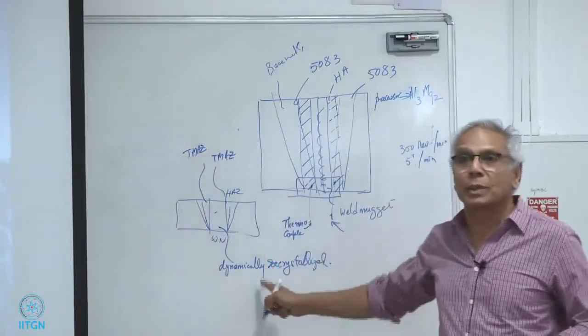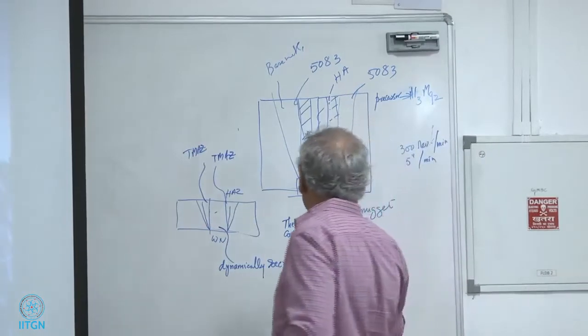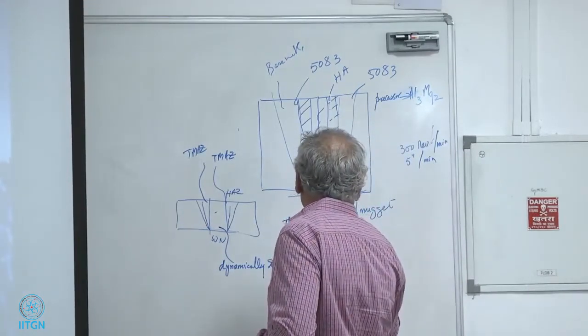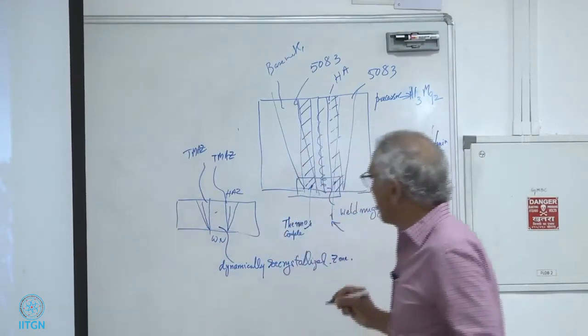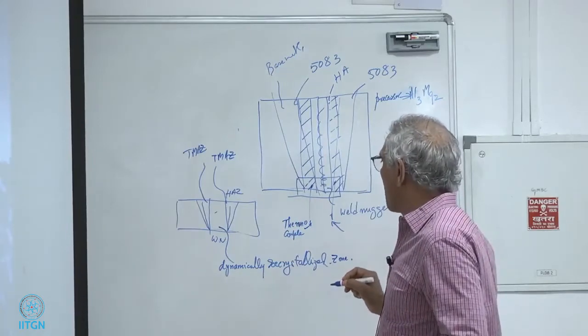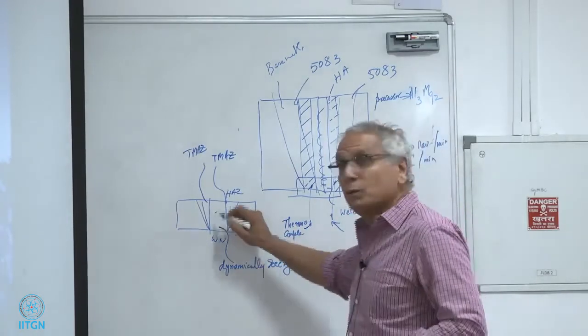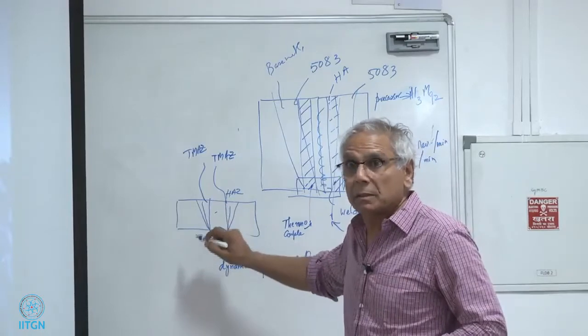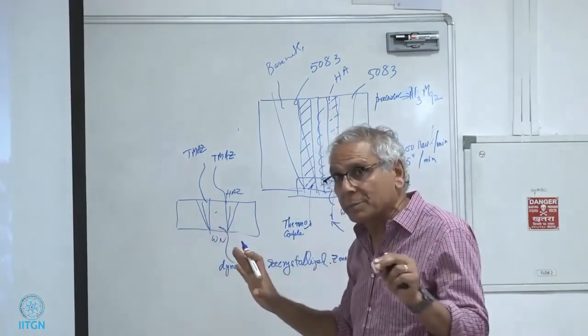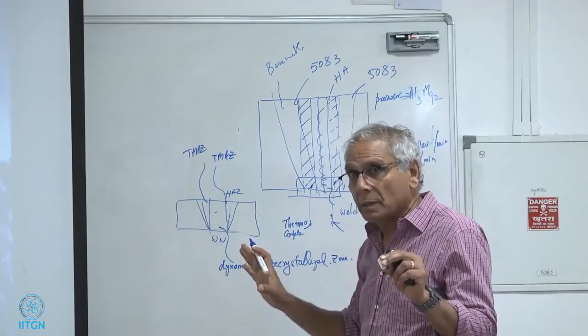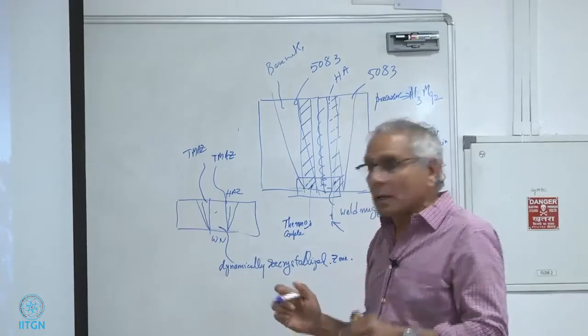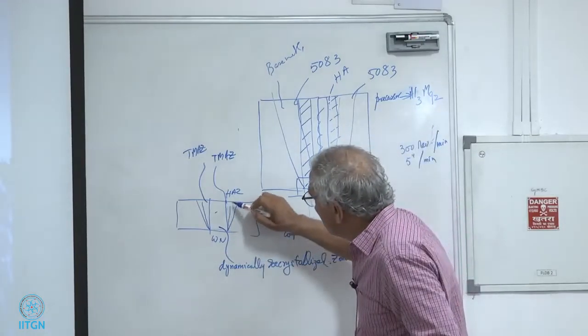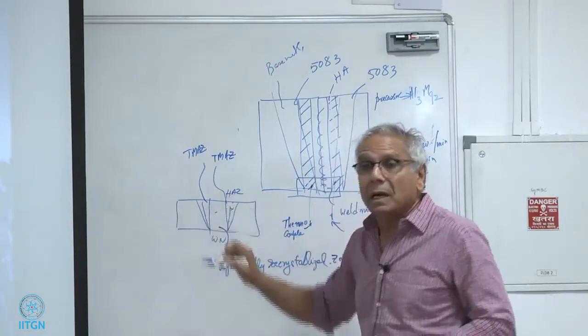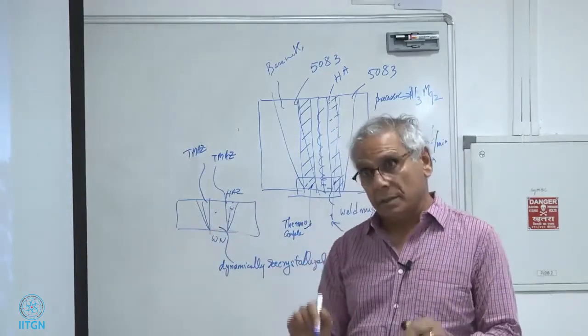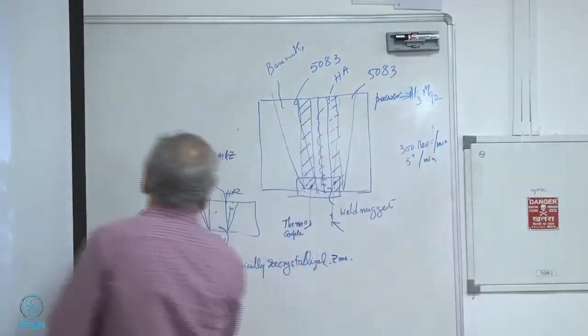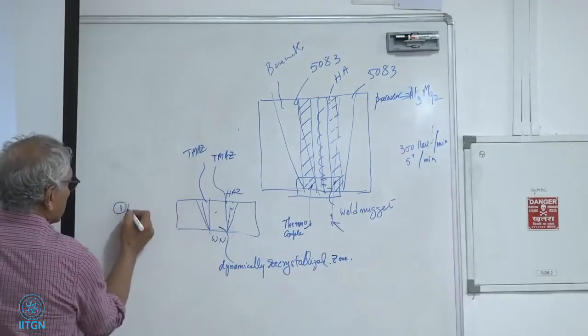I have a paper on this one, okay? Dynamically recrystallized zone, dynamic recrystallization. So here there will not be any precipitates in the weld zone. The weld zone will not have any precipitates after friction stir welding. And then you want to see where the precipitates are. Are they along the grain boundaries? So this is as friction stir welded.